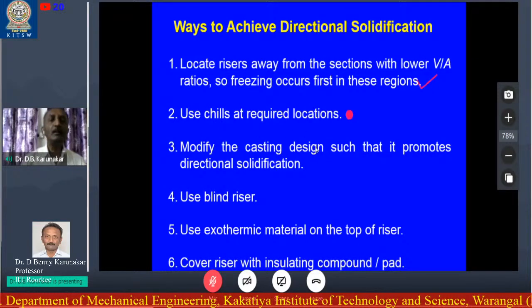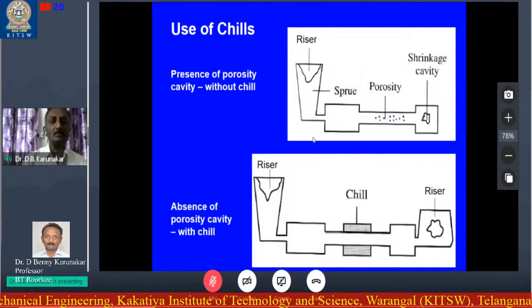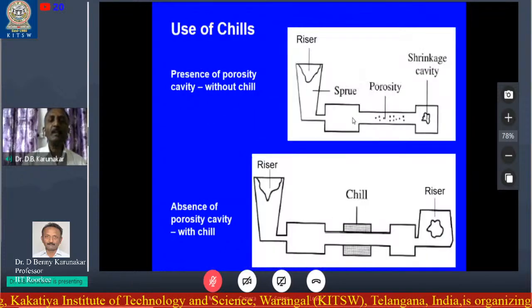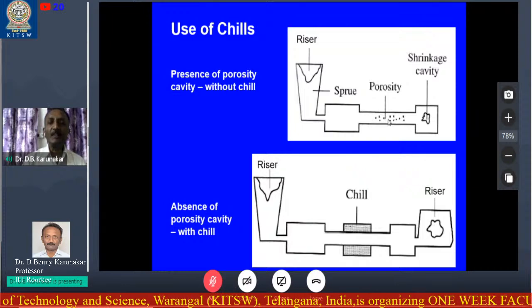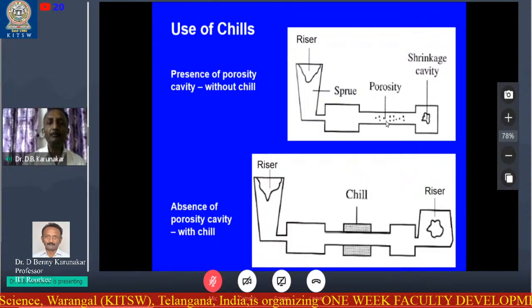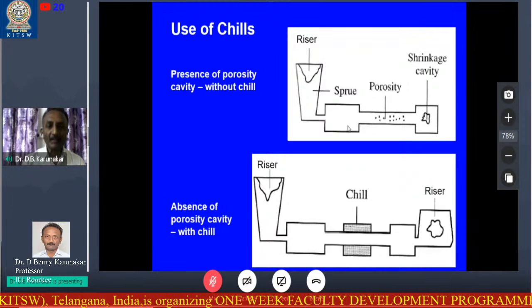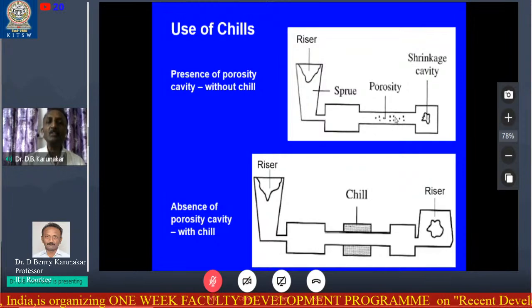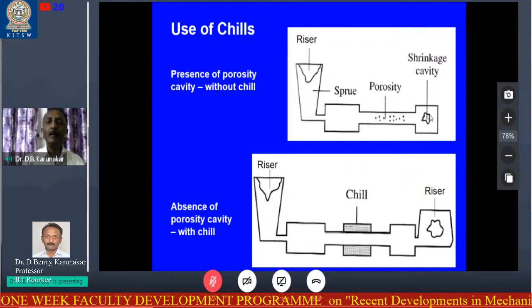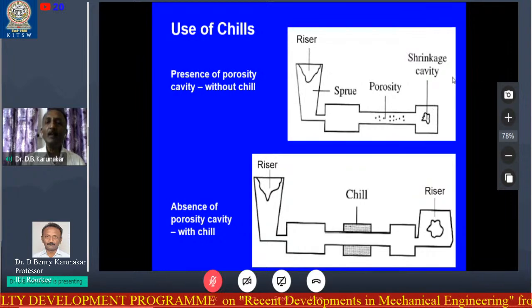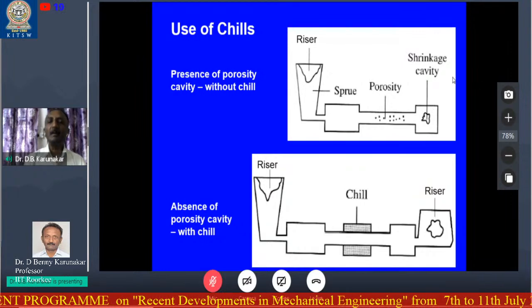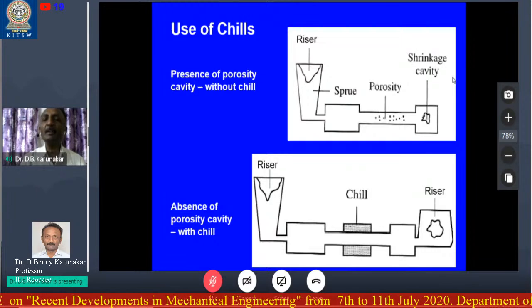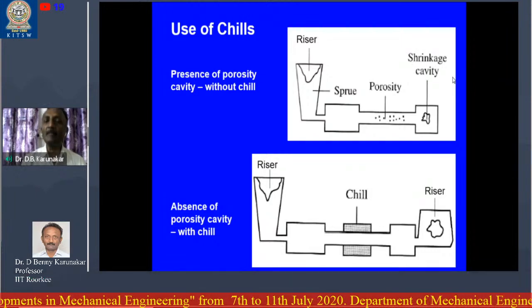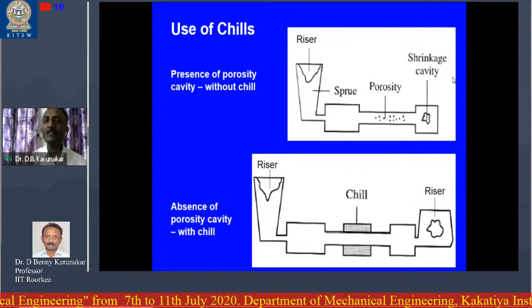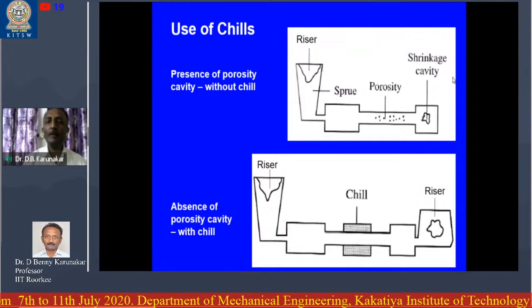Use chills at the required locations. You see here, in this case, there is gas porosity or shrinkage defect. The riser is here and this portion is solidifying first, and the portion on the right side is not able to receive the liquid metal from the riser. Why? Because the central portion is already solidified.